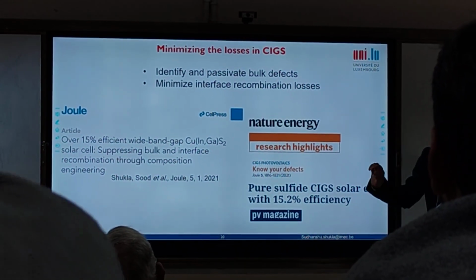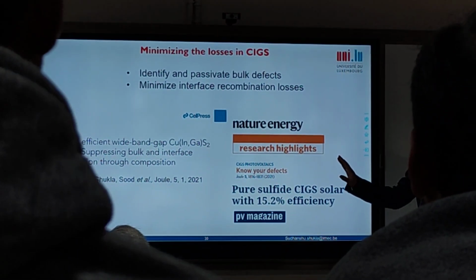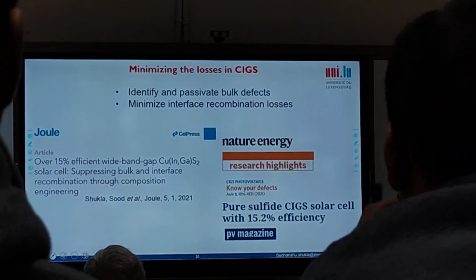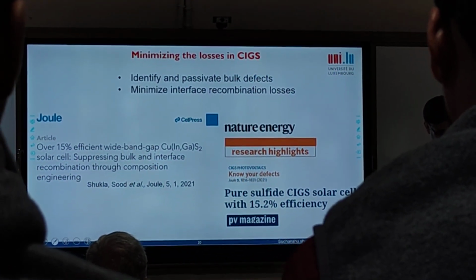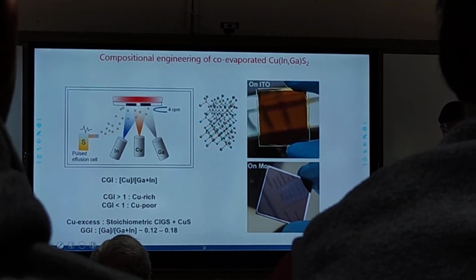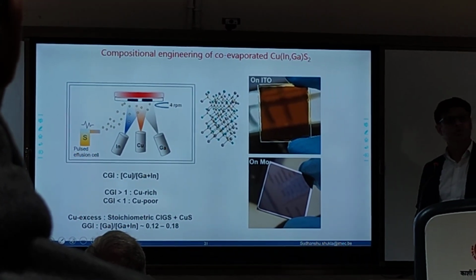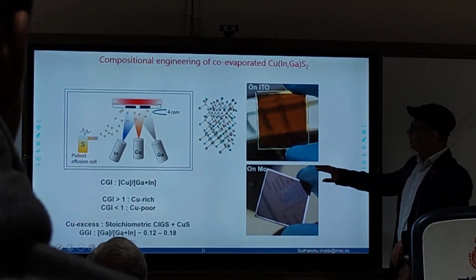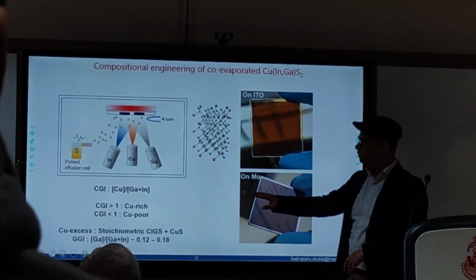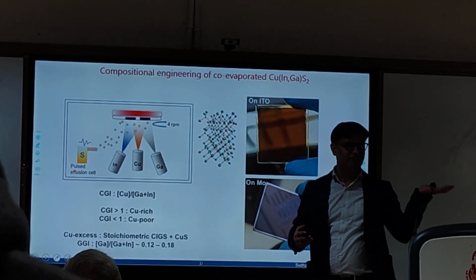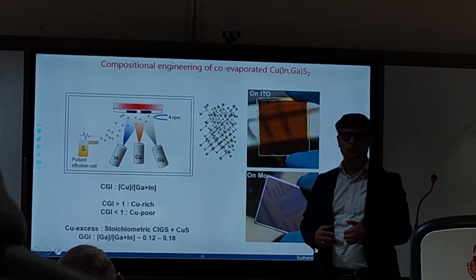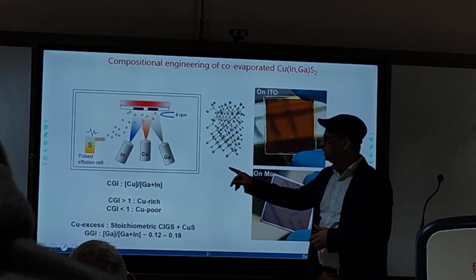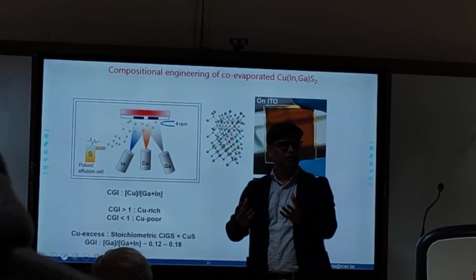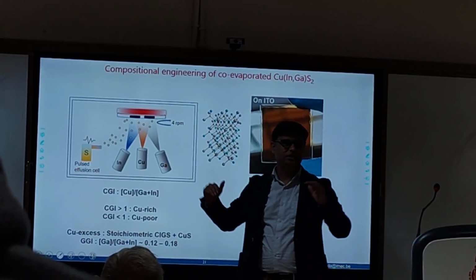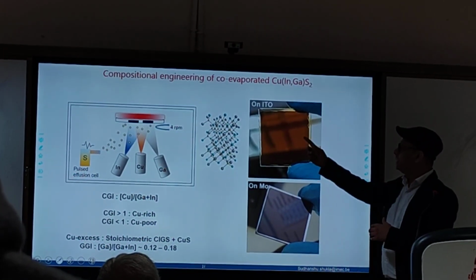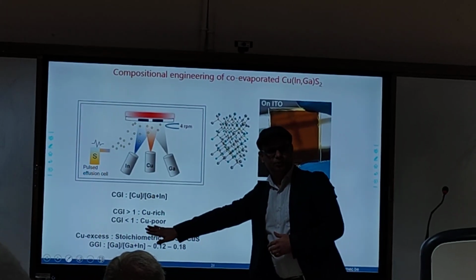Okay. So all the research, the stuff that I want to show you today is actually published. We published in '21, which actually gained quite some attention also, because this was the highest efficiency reported at that time. So the keyword here is composition engineering. Let's say I started making the CIGS. How do you make it? Of course, there are several ways you can make it. You can do solid state synthesis, which is quite popular over here. You do solution processing. This was co-evaporation. You take copper, indium, gallium, all individually, evaporate them in the presence of sulfur, heat them at temperature where it crystallizes. It makes CIGS. Now, you can tune the composition.